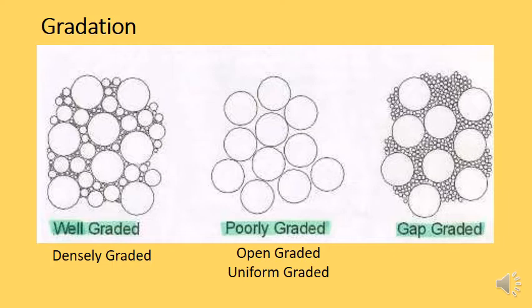Now, we need to talk about what happens when all of the particles are not the same size in an aggregate. Well, if they are all the same size, that's what we would call poorly graded. Other names for this would be open graded or uniformly graded, and you can see that with the middle section there. And you can see it's got big voids going between the particles. Now, on the other end of the spectrum, on the left, you have well-graded aggregate. This is where the aggregate particles are a range of different sizes. Another term for this is densely graded. And you can see there that there's very little in the way of void content.